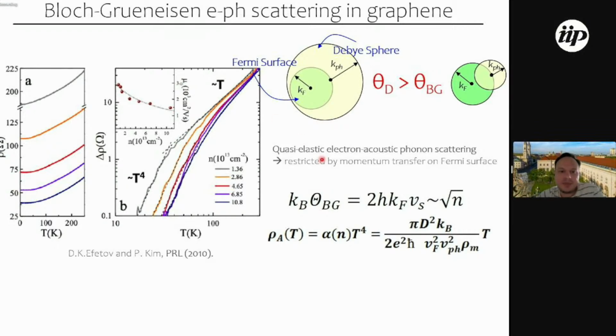And basically the Bloch-Grüneisen physics here dictates the following. This electron-phonon transport is basically explained by quasi-elastic electron-acoustic phonon scattering, which is typically defined by the Debye temperature. In normal metals, you have really large Fermi surfaces and relatively low Debye temperatures, and you get into this linear temperature regime only above a temperature defined by the Debye temperature. And usually this is hundreds of Kelvin.